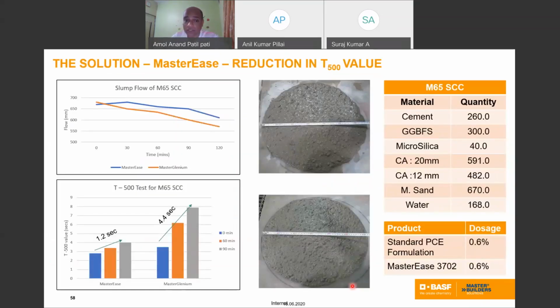Now here we are measuring the rheology property of the concrete by using the L box, V funnel, and slump flow. See here, this is the flow of this typical SCC. Okay, we will jump directly to the T500 with the flow. I hope you understand T500 in the slump flow. Here is the change. With the normal admixtures the change is 4.4 seconds across 0 minute, 60 minute, 90 minute. With the same change using the Master admixture it is hardly 1.2 seconds. So this T500 reading indicates the rheology retention in the mix.